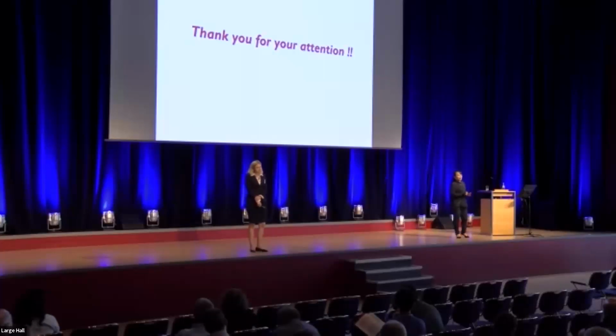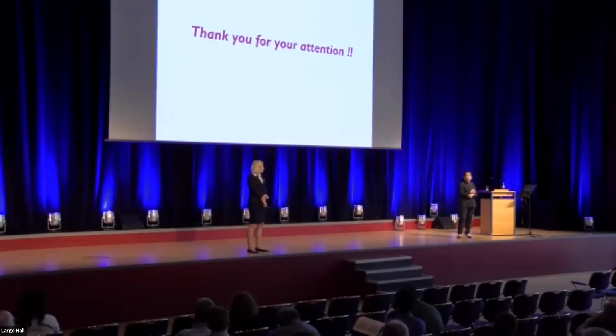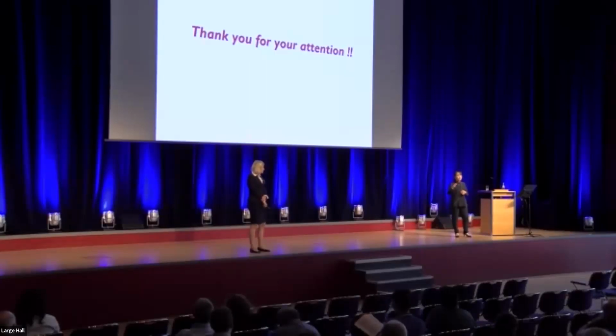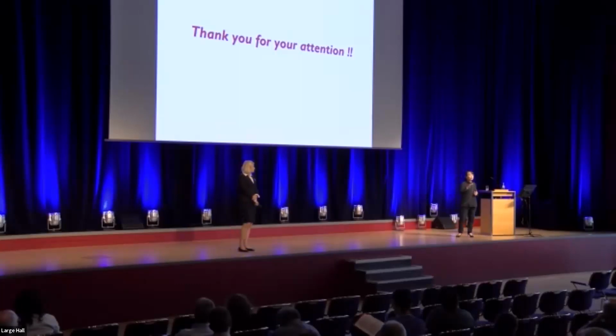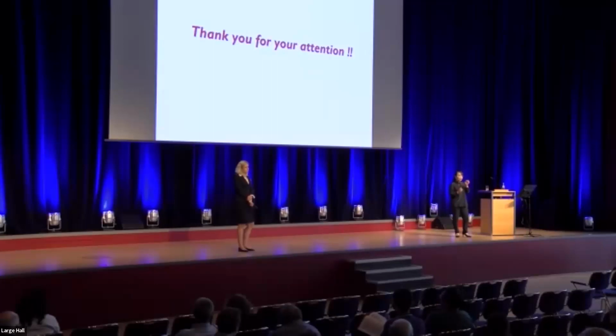Thank you. Actually, this is possible because of our students' hard work. They try to find the very optimum condition. First we prepare the core MOF. Then when we grow the second MOF, we need to find the proper concentration. We test that concentration. At that concentration, mostly we do not obtain the shell MOF itself. It means that it is a quite diluted concentration. Then when we put the core MOF into the solution, it starts to grow on the surface. So the concentration control is very, very important to cover each core crystal.